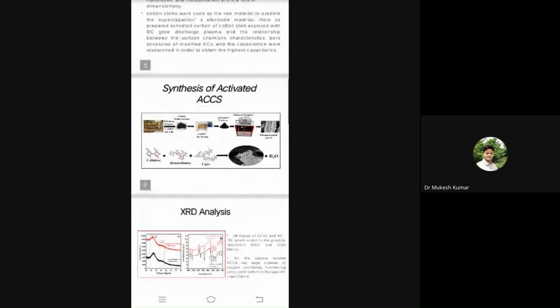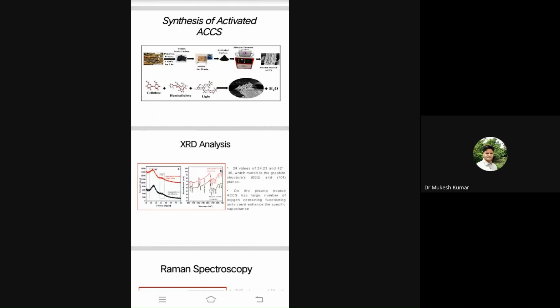Next we see the synthesis of activated carbons. ACC is activated carbon, cotton stalk. We collect the cotton stalk and put it through the pyrolysis process at 400 degrees Celsius for 1 hour. Then the cotton stalk is placed into the muffle furnace at 600 degrees Celsius for 30 minutes, giving an activated carbon of cotton stalk, and this activated carbon is ground into nanopowders. This nanopowder is placed into the plasma chamber, which will change the surface of the nanoparticles.